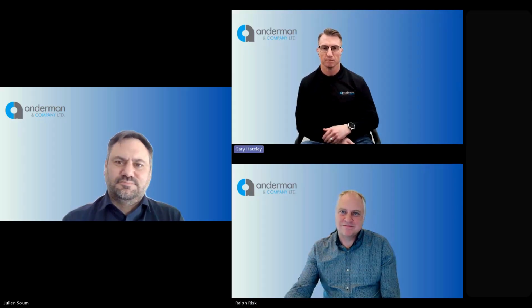And Gary, one practical takeaway from your side? Yes, along the same lines, Ralph. One practical takeaway would be to involve Anderman early to avoid costly misspecification. In advanced ceramics, failures rarely stem from choosing a bad material. They normally result from a mismatch between the microstructure and the environment, the stress state, and the manufacturing constraints.